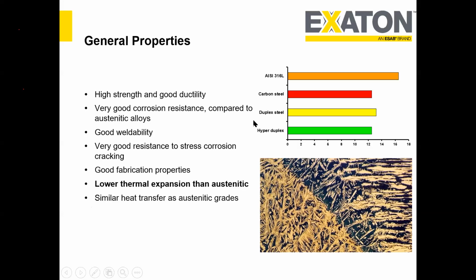If you see here, it gives the typical thermal expansion values. It is important to note one more thing, that for carbon steel and duplex stainless steel, the thermal expansion is almost the same. So when you do dissimilar welding, it is much more compatible, even compared to 316L. Yes, we do a lot of dissimilar joining of 316L to carbon steel, but if we compare carbon steel to duplex, it is much more suitable in comparison to 316L. Okay.